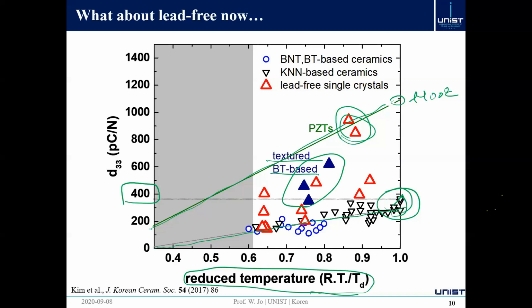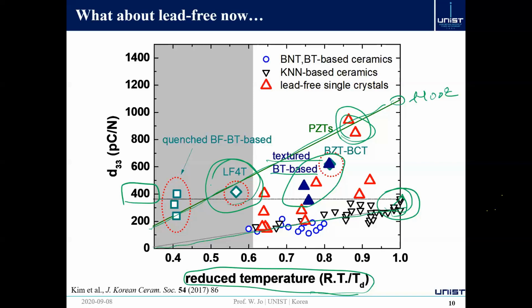And this is from the textured BT-based materials. You see that at least this is far away from the limitation here. And this is a well-known composition from the Nature paper, Saito et al. As you can see here, the reason this material became really famous is because it fits very near to the PZT line here. Of course, inside this is the processing window, so this is really workable. And another interesting point is that the water quenched bismuth ferrite-based material also fits into the PZT line here.